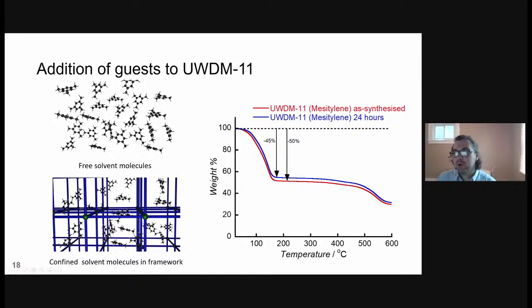The other reason we chose mesitylene is that it's very non-polar, and it doesn't have anything which is going to interact via a hydrogen bonding type interaction, for example, with the benzimidazole moiety on the rotaxane. This is important as we don't want to introduce competitive binding, which is going to have a significant effect on what the crown ether is doing at those benzimidazole recognition sites.